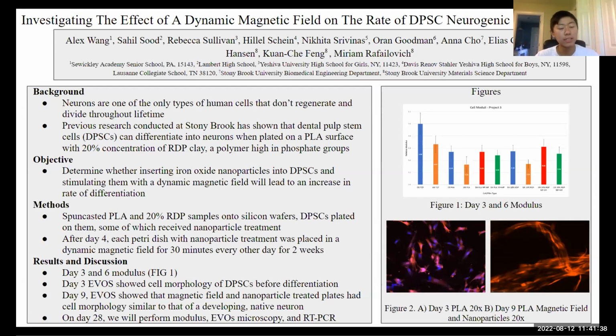Yeah, so we conducted multiple testing for data collection throughout this experiment. The first one we did was on day 3 before neuronal media change from the dental pulp stem cell media. And we basically did modulus testing where we tested the rigidity of the cells in 3 different spots and on 3 different cells on each plate of the controls. So that would be on the TCP plates and also the PLA plates before any sort of magnetic field or nanoparticle treatment.